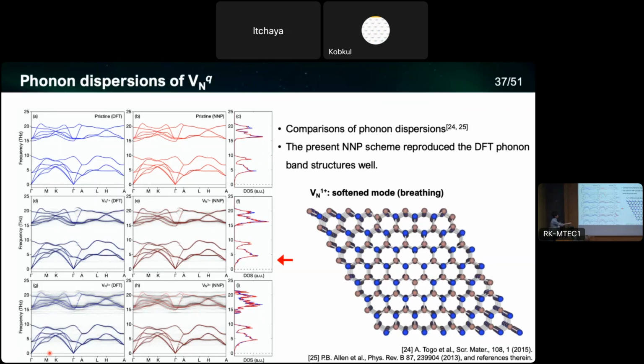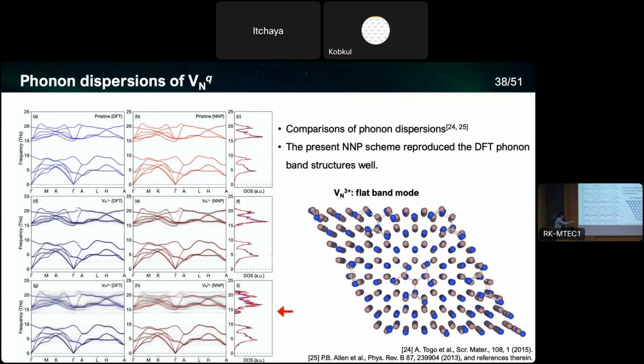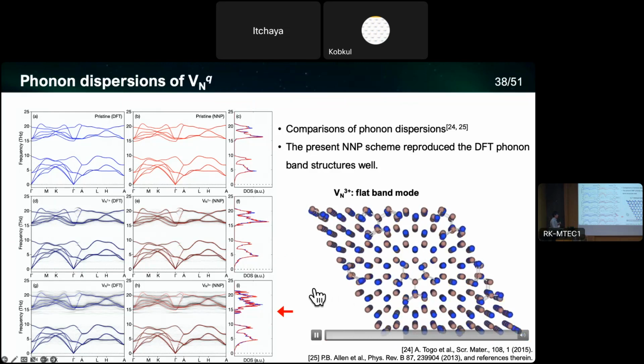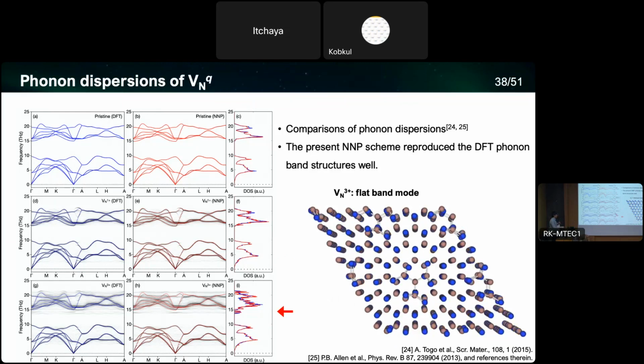And so actually there is a softened phonon state which corresponds to this kind of breathing vibrations. This position is the nitrogen vacancy, and the atoms surrounding the nitrogen vacancies are vibrating toward the vacancy positions. And this is for the case of the +3 charge state. The distinctive feature is the flat band at the upper part of the band gap. And just for your reference, these are the vibration states of this flat band.